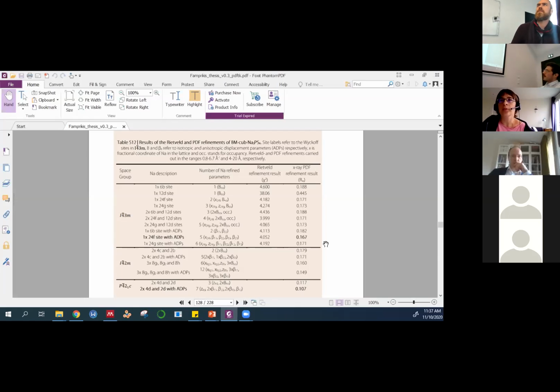First, what I missed is that I don't have the occupancy of those sites. For example, of course, if you put one sodium in 6B for the first model and one in 12D, you don't have the same number of sodiums. So probably you applied some occupancy factor that you didn't mention. Did you? I do mention here the number of refined parameters. Whenever there's more than one sodium, I'm including the fact that I am fitting the occupancy. But I did not put the results, indeed.